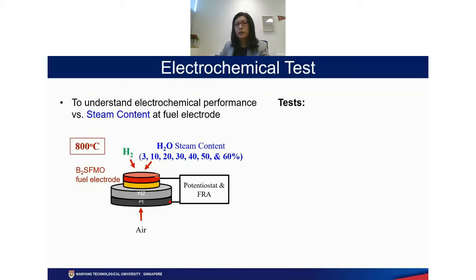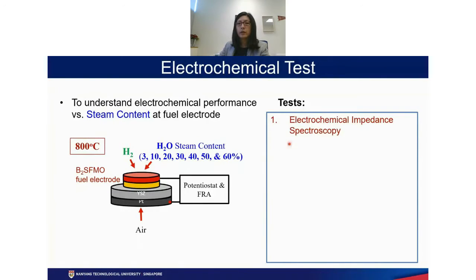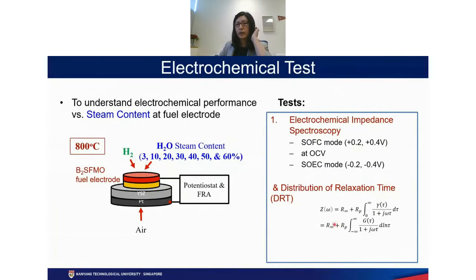We perform the tests, including electrochemical impedance spectroscopy under SOFC mode at 2 different voltages, at OCV, and also under SOEC mode. Then we extract from the EIS result to do the DRT, to identify which process is most affected by the changing moisture content. And we also check the polarization curve, the IV curve, to see the overall performance.